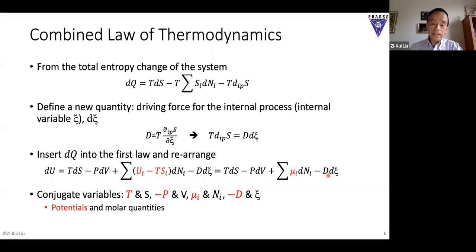Now it's also very important that you see for this fundamental equation we derived, we have these pairs: TS, PV, mu i, Ni, and d xi. So we call them conjugate variables. The temperature and the entropy. No minus P here because we have minus some there. So we usually move minus P inside here: minus PV, and mu i, Ni, and minus d xi. Okay, now what you see here is that these red ones we call the potentials. They are homogeneous at equilibrium. And the other ones are called molar quantities because they depend on the size of the system.